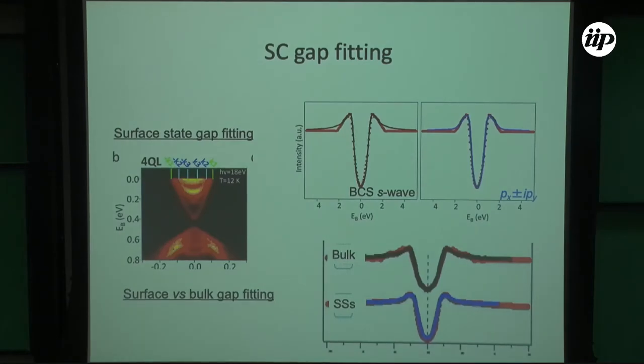Now, it goes back to your question: can we fit the coherence peak and get more information? That is what we're trying to do here. Before doing that, I'll also tell you the challenge. Your Fermi level is in the conduction band, not in the surface states alone. So when you are measuring, you have to select K values. But it also gives us one advantage: we know that the surface state merges with the bulk at the edge of the band, so this is surface sensitive, and this is more bulk-like.